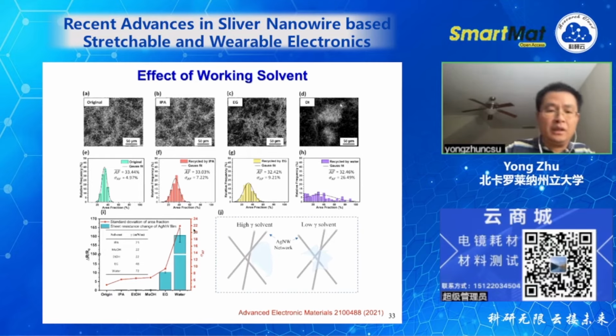And then we measure the resistance also, after the recycling. You see using the original and the IPA, and this is the ethanol and so on, the resistance is good. But using EG, especially DI water, the resistance increases a lot. That is consistent with the fact that with DI water, the distribution is not uniform. You have local agglomeration.